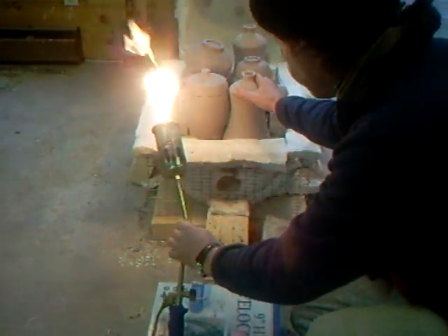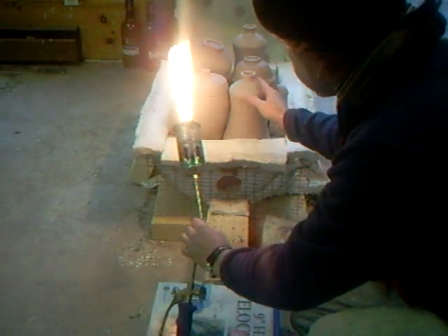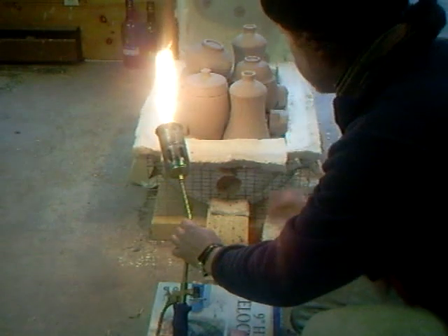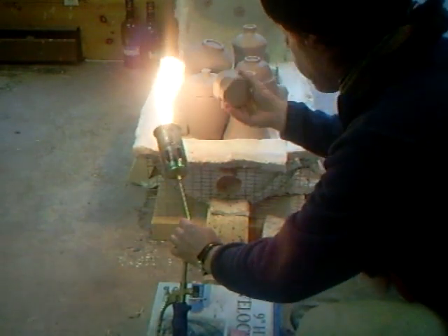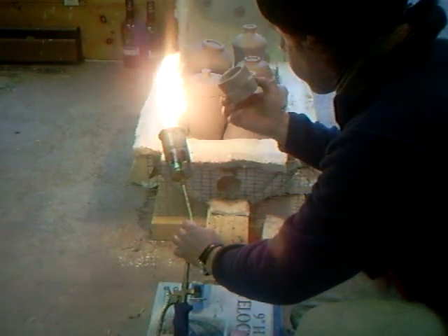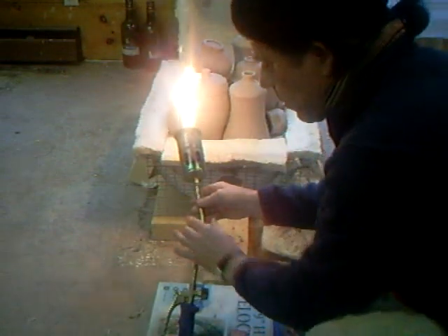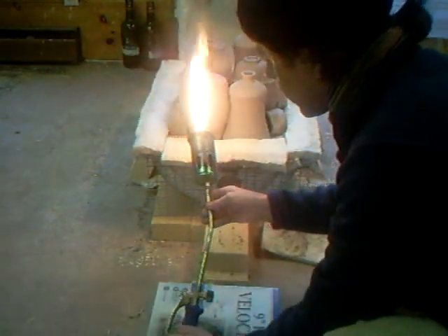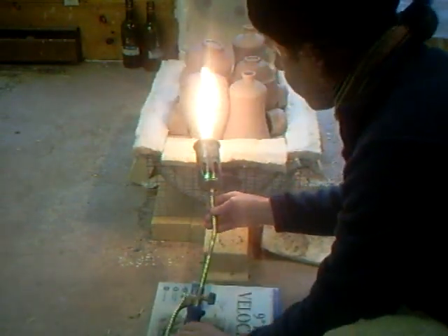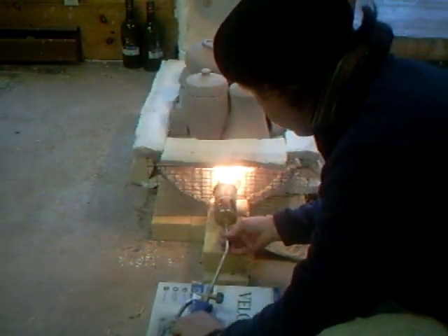Because remember, these pots are cold. They more than likely, in this case, are completely dry. But some of these nut and bolt pots, you just don't know. They look dry on the outside, but on the inside there could be a bit of moisture. So just as a precaution, we're going to go really slow. Whatever firing you do, you start slow — especially if you've got raw ware in there. We're going to start slow.